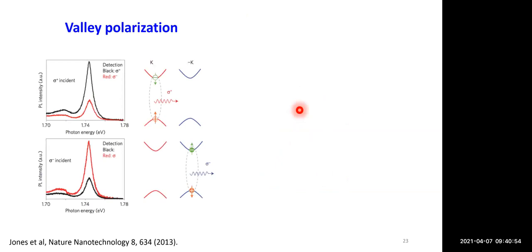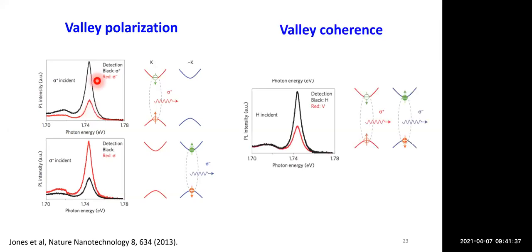In the polarization resolved photoluminescence experiments that were performed on these monolayers, what was observed is that you can use a laser to selectively excite electron hole pairs in a valley, which can then form valley polarized excitons. Thus the exciton, along with the free electron and hole, can also have this binary valley pseudospin. As you can see in the PL spectra taken by this group in Washington, they have shown a stronger emission in the copolarized spectra than the cross-polarized spectra in red. This basically creates your valley polarization.